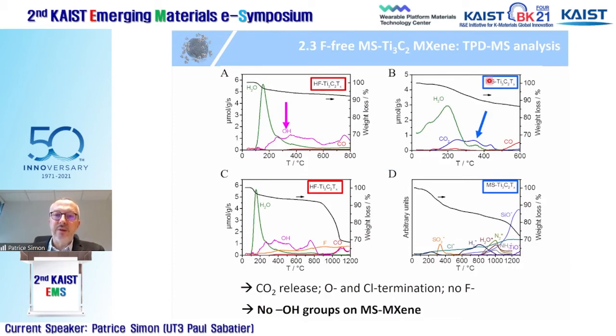Now we did some thermal programmed desorption mass spectrometry analysis of these materials. In fact, it's a TGA connected to a mass spectrometer. And this is here an MXene, Ti3C2, prepared from HF etching, a conventional MXene with fluorine terminations. So you can see that up to 800 degrees Celsius, you have a water departure, and you see OH groups here on the surface.